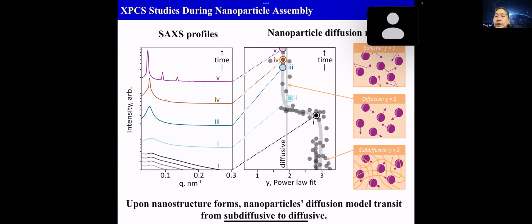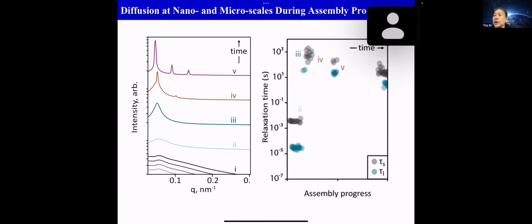And we wanted to look at the mobility. This is why we decided to look at the relaxation time as a function of Q. The idea is that if you have a short range diffusion, that means you have a higher Q, that's nanoscopic.